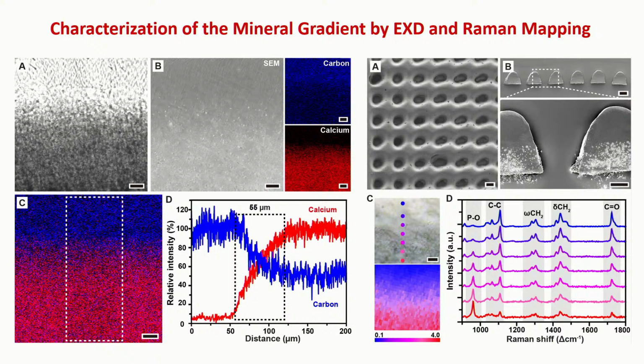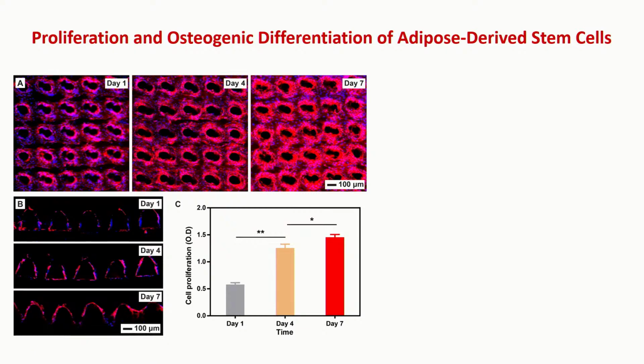So you can do mapping. Eventually, you can generate this kind of map. You can see a gradual change of mineral content from the bottom to the top. And the PCL concentration also decreases from top to the bottom. So it's like an opposite gradient for these two different materials. When we seed, again, stem cells onto this scaffold, first we can see the cells are pretty happy on this scaffold. So you can see increased proliferation for these cells as a function of time.